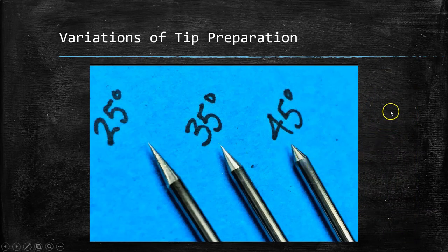And now here we see those variations in tip preparations that I mentioned earlier. If we start with a 25 degree taper, we see that the length of the taper is longer, and it also results in a much narrower tip. Whereas a 35 degree taper is not as long, and we see that the tip is a little bit wider. And with a 45 degree, we see that the taper is much shorter and it is much more blunt than a 35, and definitely more than that 25.